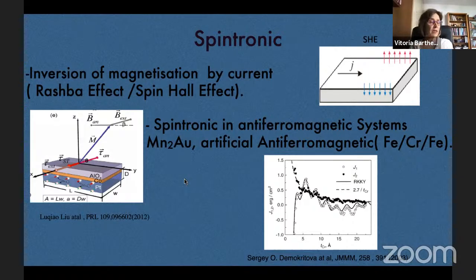So it's very interesting to make this in the device. But at the same time, there are no magnetizations to turn, because there are no net magnetizations. But there are special antiferromagnetics like manganese gold that have a break of symmetry, a magnetic symmetry, that has generated an electrical field that, when the current passes in this material, a polarization is created. This is called the Rashba effect, or spin Hall effect. Both are related with the appearance of a polarization that will shift the magnetizations.